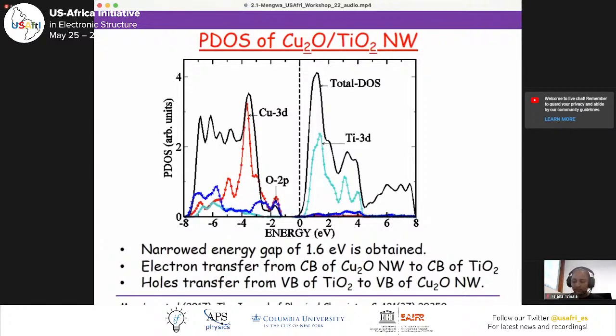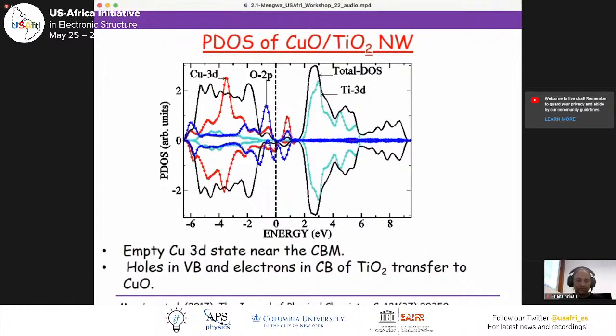The electron transfers from the CB of Cu2O to the CB of TiO2. Similarly, there is hole transfer from the valence band of TiO2 to the valence band of Cu2O. Therefore, electrons are transferred to the conduction band of TiO2, while holes are transferred to the valence band of Cu2O. This leads to charge separation, and therefore it suppresses recombination.